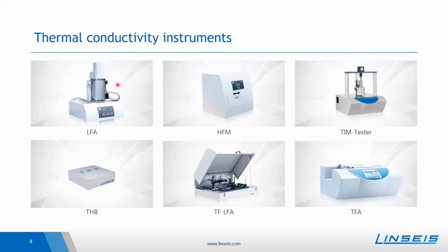So the laser flash analyzer is the most universal instrument for thermal conductivity determination, as it covers a very broad thermal conductivity and a very broad temperature range. The THB is also suitable for a broad range of applications, and for thin films, we have the TF-LFA, which uses a similar technique to the LFA, and we also have the TFA, which is also used for thin film analysis.